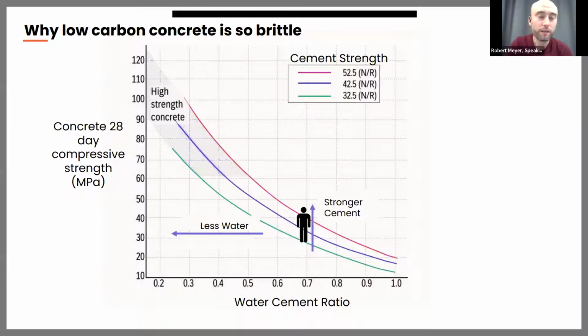But if you now phone up the concrete plant and you order something much more difficult to make, let's say you want some high strength concrete with a water cement ratio of 0.35, then people will start to get nervous in the plant, and the mixing operator will not be able to do this alone, and he will be accompanied by 1 or 2 lab personnel. And they will make loads and loads of tests at the plant and look over the shoulder of the mixing operator to really make sure that the concrete has the right consistency and the right amount of water in it, and will really take care that everything goes well. And even one of them will join the concrete on its way to the construction site and remain at the construction site and do further testing to make sure everything's fine and there are no severe consequences.